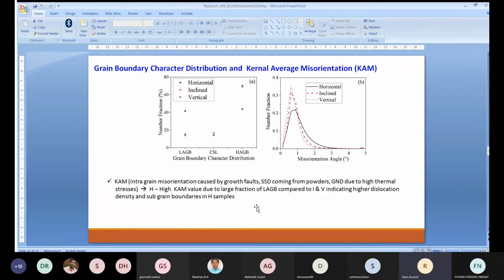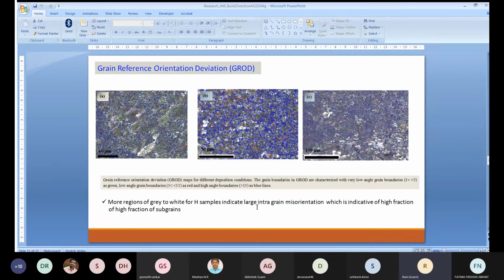If you have a high KAM value, it indicates that you have a large fraction of low angle grain boundaries. This large fraction tells that you have a high dislocation density inside the grain and a greater number of subgrains or subgrain boundaries inside the horizontal samples. And we didn't leave it there. In order to validate the KAM result, we did grain reference orientation deviation.